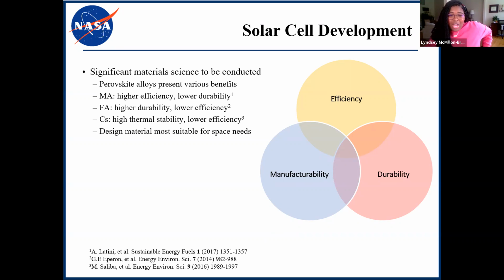So it's already pretty well accepted that methyl ammonium lead iodide has a high efficiency and a lower durability. There are some concerns with the durability because it can undergo a structural phase transition at about 55 C. They are susceptible to moisture-induced degradation and some thermal stability issues. Also, light-induced trap states can form, and some halide segregation can happen in the mixed halide perovskites.